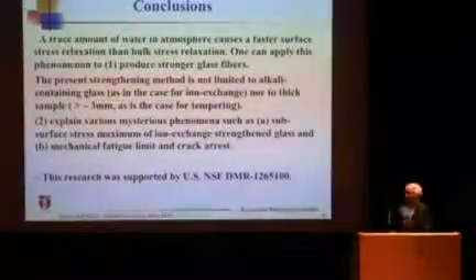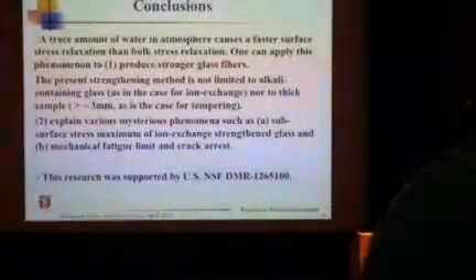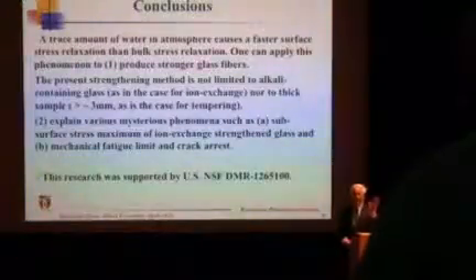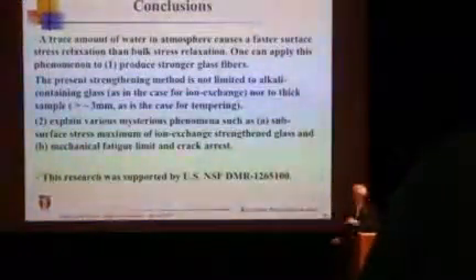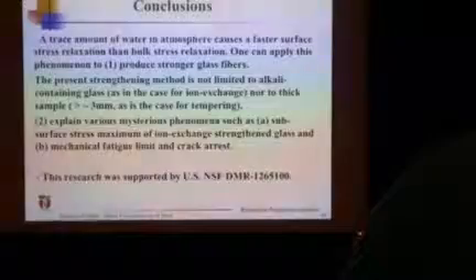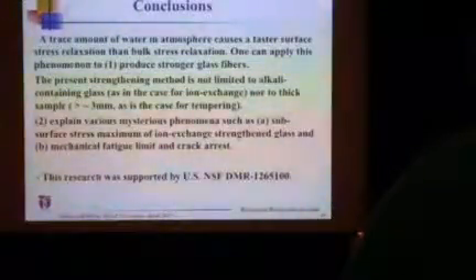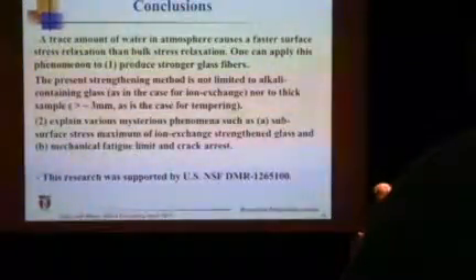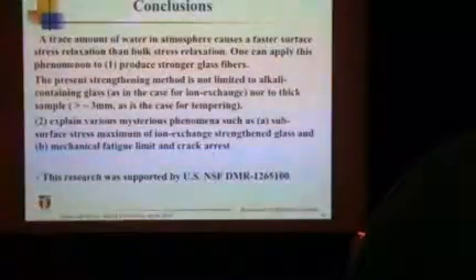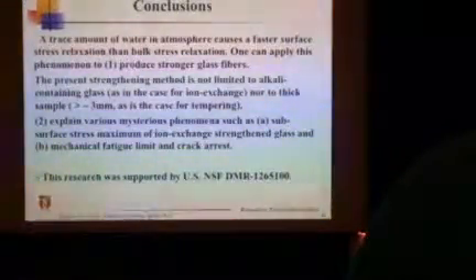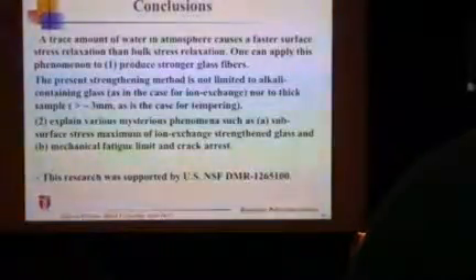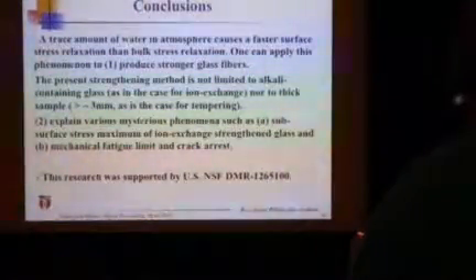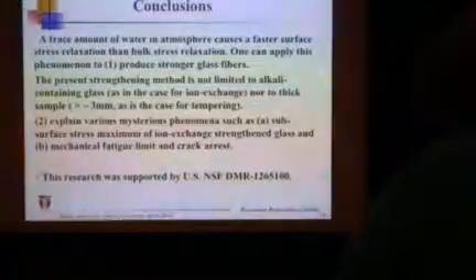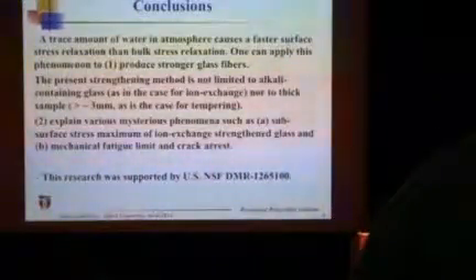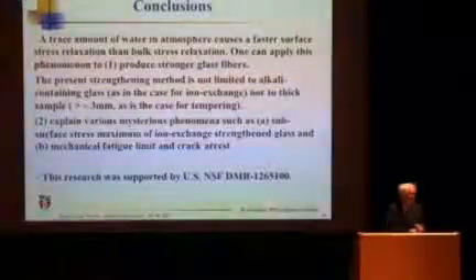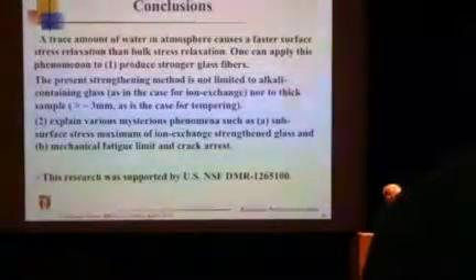One of them is the subsurface maximum, the surface compressive stress made by ion exchange strengthening. And that can be explained by surface stress relaxation. The second one is the fatigue limit, which can be accounted for by using the idea of surface stress relaxation. And that is, at least, the fruits we have obtained. Whether it's sweet or sour, we shall see. So that's my conclusion, and I appreciate your attention.